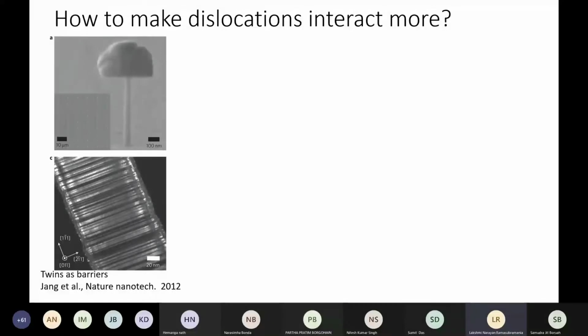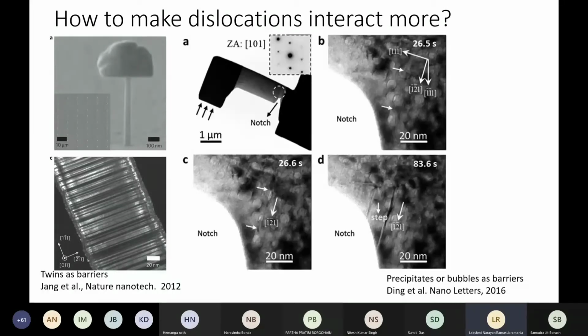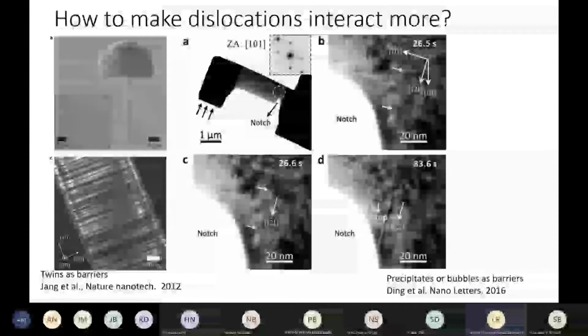And here twins are being used as barriers. Wherever a dislocation starts propagating, it goes and encounters a twin boundary. And it cannot move further because the orientation across the twin boundary will be different, and this dislocation cannot go through them. Another way is to use irradiation based bubbles. So here helium bubbles have been put in the sample where they interact with dislocations and don't allow them to pass through. So you're essentially making sure that dislocations are not able to exit the crystal and to interact with other dislocations in the crystal to give more strength as well as higher plasticity.